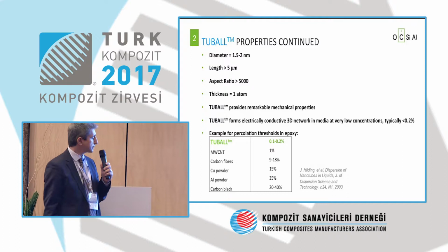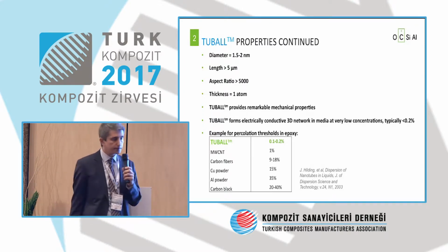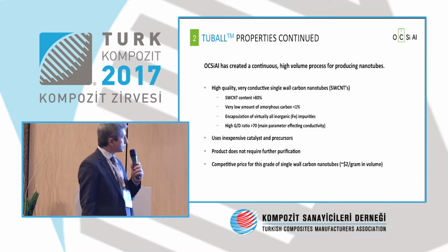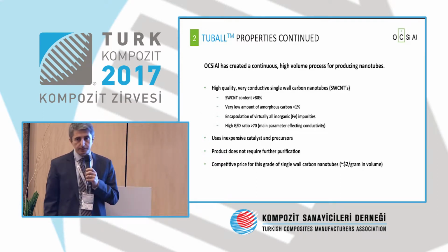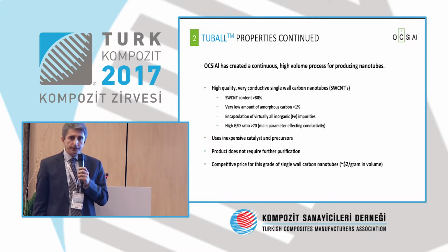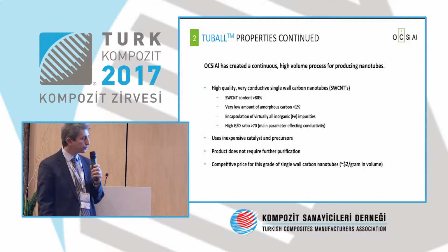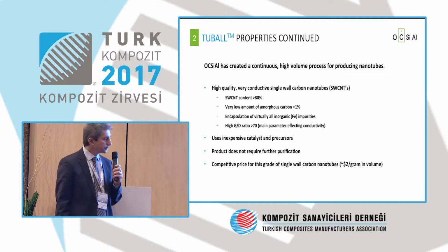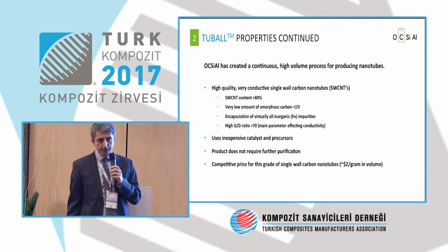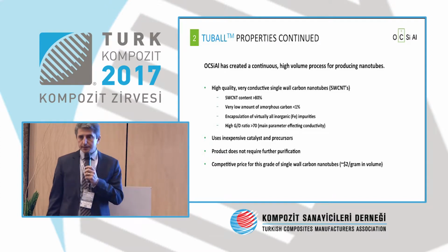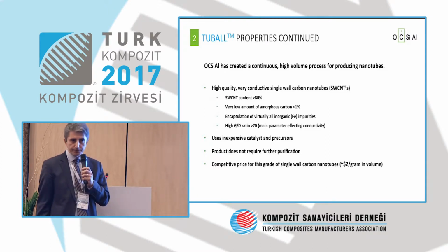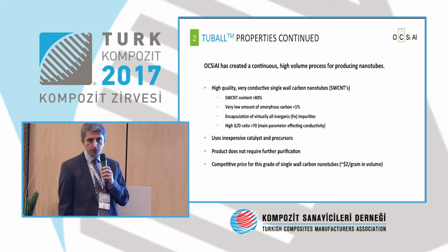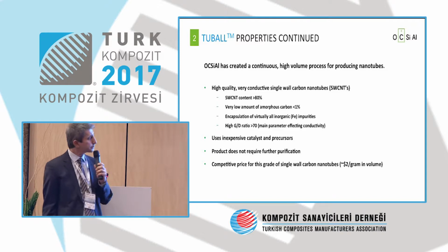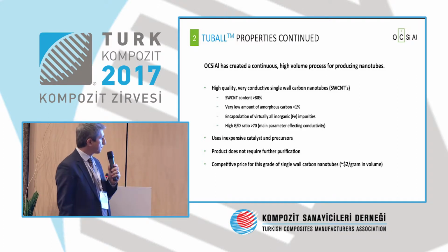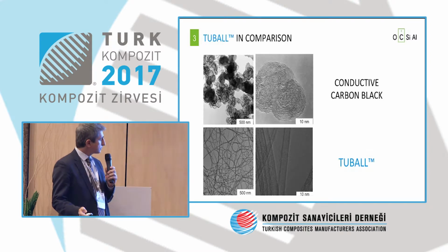It gives us a great advantage in weight. Rather than contribution, it's actually additional contribution to the material. The high quality and very conductive single-wall carbon nanotubes, the SWCNT content is more than 80%. And in general, within the material, there's a very low amount of amorphous carbon at about less than 1%. And the encapsulation of virtually all inorganic impurities. It is not easily degraded, which is one of the most important features of this material.